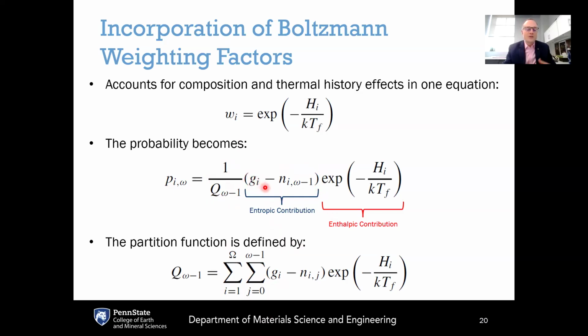So the total number of, say, aluminum atoms minus the number of aluminum atoms that have already been selected. So it's just the total number of atoms that are remaining to be selected that don't already have bonds to the network modifiers. That is the entropic contribution, this entropic prefactor, and then multiplied by this Boltzmann weighting factor that gives the energetic or enthalpic contribution.